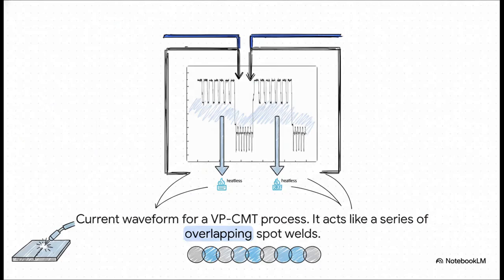If you look at the waveform for CMT, you can see these moments where the current just plummets to nearly nothing. That's the magic. That's the mechanical retraction phase. Because there's no final energy surge to detach the droplet, the heat input is incredibly low. It's kind of like creating a seam by laying down a perfect series of tiny overlapping spot welds.